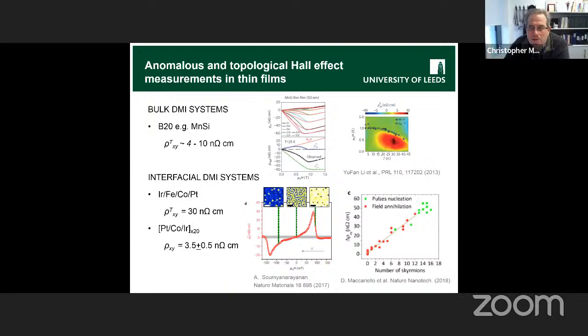Now, at around the time we were getting interested in this, of course, we were not alone. Other people were looking at thin films. This is a thin film of manganese silicon. Again, you can see this Hall signal when you subtract out the other bits, where you can pick out this Skyrmion phase. Or people were just starting to look at these multilayer interfacial DMI systems. And there were a couple of publications that came out whilst we were doing our experiments.